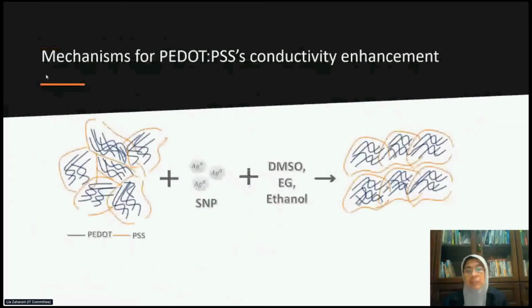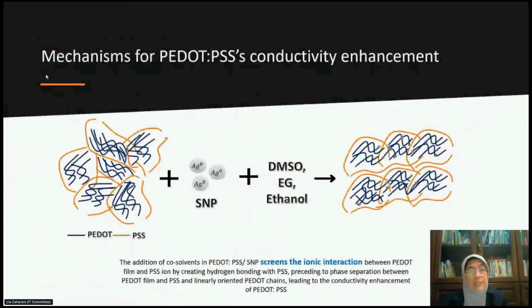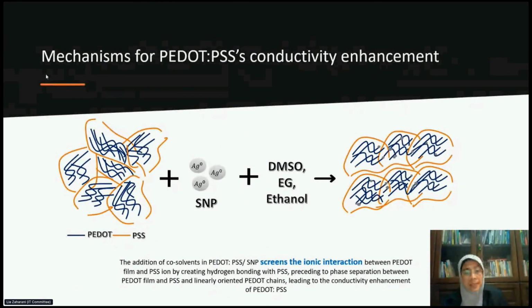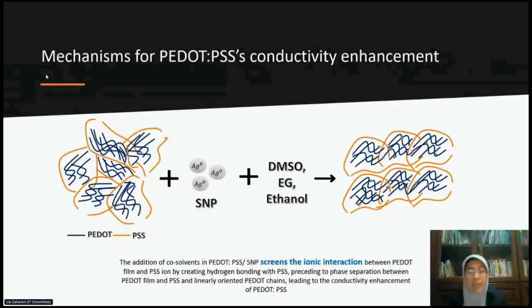Then the mechanism for PEDOT:PSS conductivity enhancement. Let us go through it, it is very nice to see the mechanism. We can see that with the addition of co-solvent in PEDOT:PSS, it screens the ionic interactions between